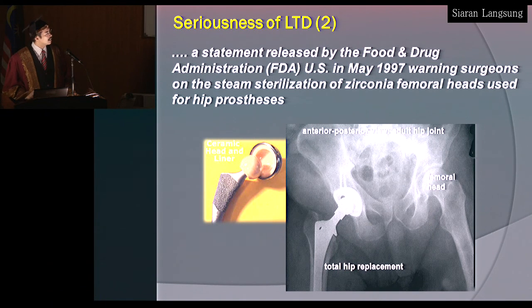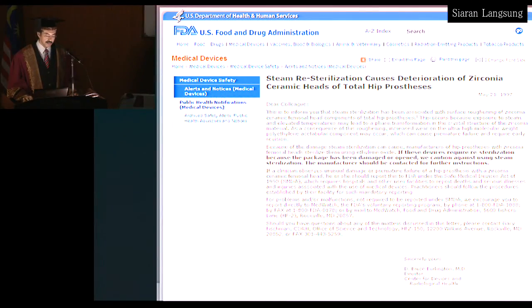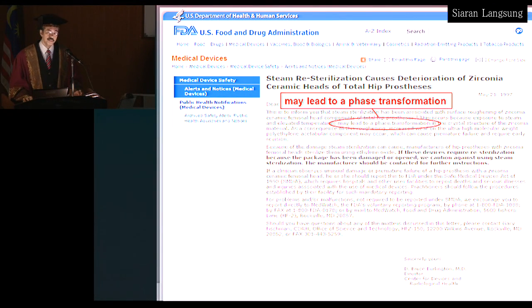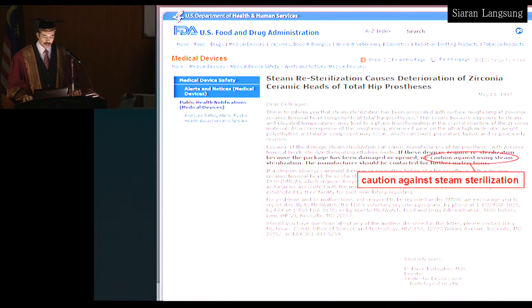So in this case, the head is made out of zirconia, and the cup, as you can see in the acetabular cup, and the stem are made out of stainless steel or titanium. The titanium stem is put in the femur, and the other part goes into the hip bone. The warning issued by the FDA is that when the zirconia head is exposed to a steam environment, it may lead to phase transformation. Therefore, the FDA has cautioned surgeons not to sterilize the zirconia head in a steam environment.